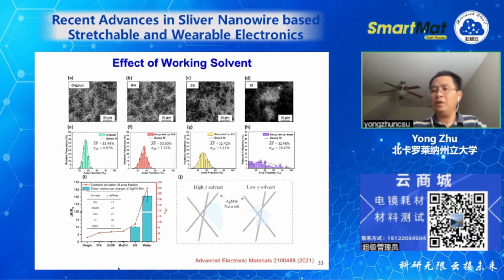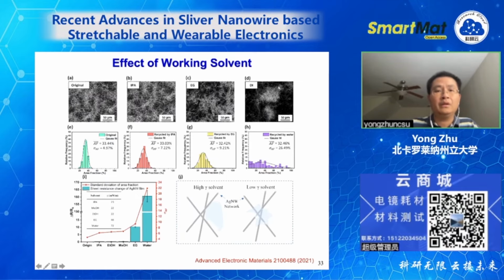Okay, a couple of details. Let me go through them quickly. So this is the effect of the working solvent. We use a variety of solvents. This is the original network structure. This is after we recycle using IPA, EG, and DI water. You can see the quality is reasonably good for the first two, but the DI water is pretty bad.